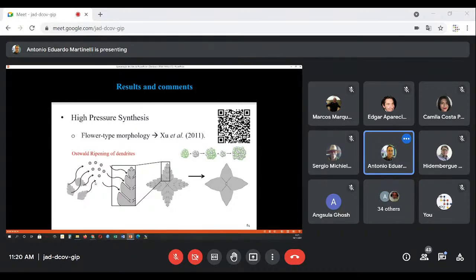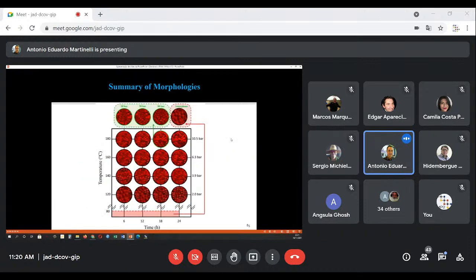This schematic here shows the formation of the flowers from Ostwald ripening of dendrites. So the dendrites that we saw in the beginning of particle growth result in flower type particles. And this work is by Xu, 2011. Here's a summary. This work also was done by Armando. It's published in his paper.